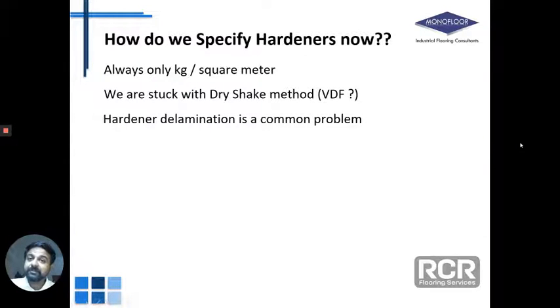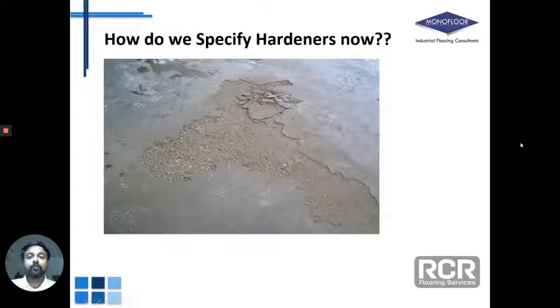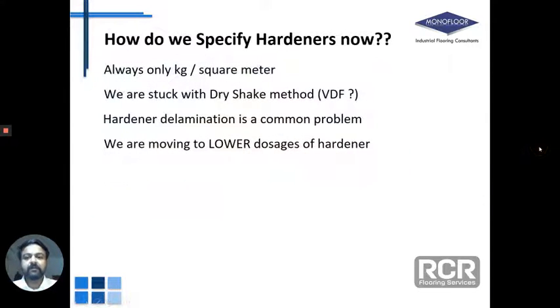Hardener delamination becomes a very common problem. If you have incompatible systems, if these hardeners don't have enough water to adhere to the surface, then this is a very common problem. You may have seen this. This is called delamination of the hardener layer. So because of the fear of delamination, we are forced to move to lower and lower dosages of hardener. We are now starting to even talk about 2.5, 3 kilos of hardener, which is not even 1 millimeter of thickness, which is very, very low.